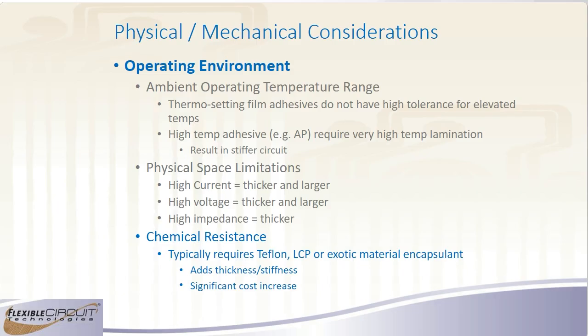The Teflon, well, there's a reason they coat pans with it, because nothing sticks to it. So it's difficult to use that as a cover material and make it stick. It can be done, but it does require a special grade of Teflon and some special handling and processing to be able to successfully bond Teflon. And LCP is kind of in that same ballpark, very difficult to work with and very expensive. It'll also add additional thickness if you have to add those layers over the top of your circuit. So chemical resistance can add additional mechanical issues that could cause problems when you're trying to install it.